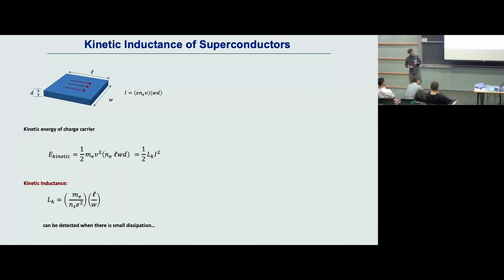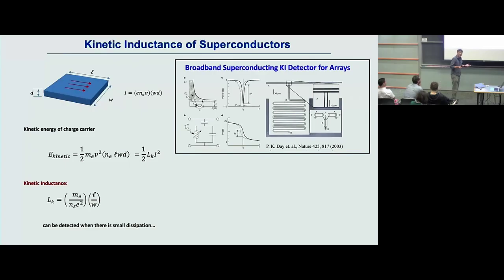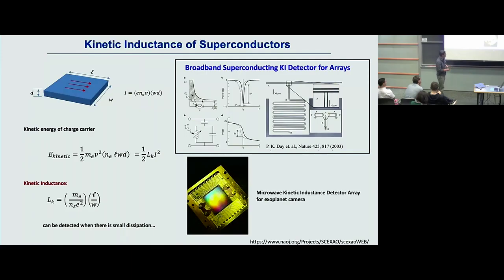However, to get an appreciable inductance response compared with the geometrical inductance, you need a really, really thin sample. So a 2D sample is ideal, but you also don't want sample resistance, which would compete with the inductance. So it only works well with superconductors. In fact, it is not a new concept. It has already been studied, and can even be used as a really practical device as a detector. Astrophysicists already make superconducting kinetic inductance detectors, send them out on space probes, and they are the standard tools now.